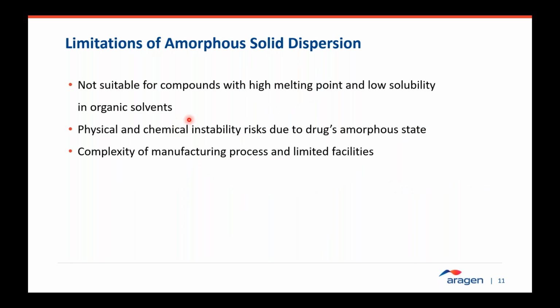There are a few limitations, though it is a highly utilized technique to improve solubility. It does come with some limitations. It's not suitable for compounds with a very high melting point or very low solubility in organic solvents. Hot melt extrusion and spray drying are the very well-known technologies commonly employed to commercialize and manufacture these solid dispersions. So if a compound has limitations in these two properties, it becomes very difficult to screen and develop a solid dispersion, and also to scale up and commercially manufacture.